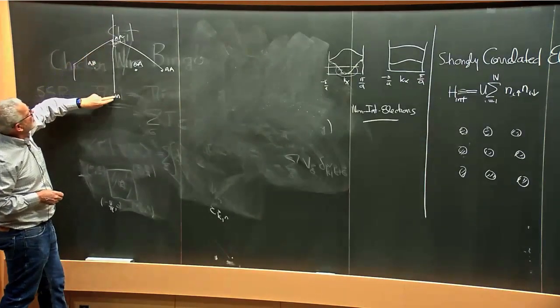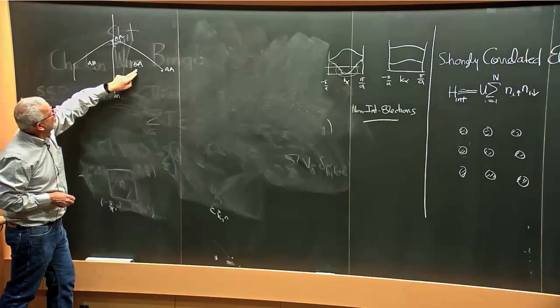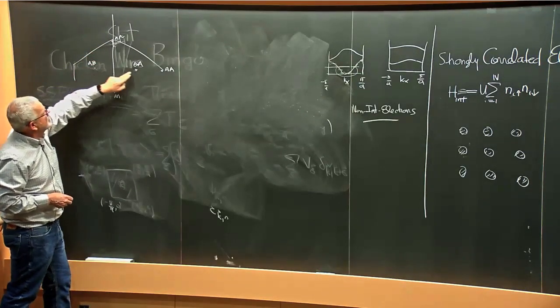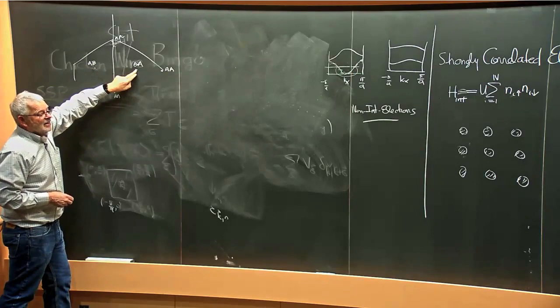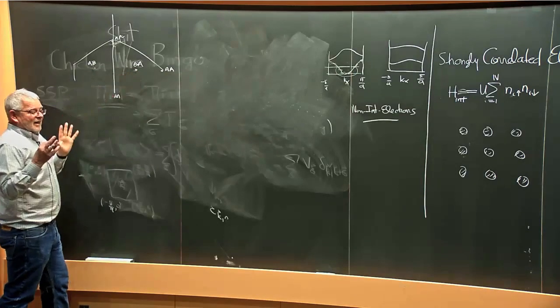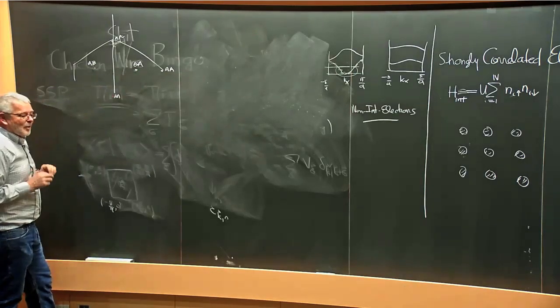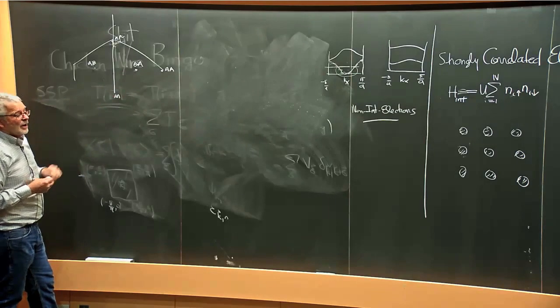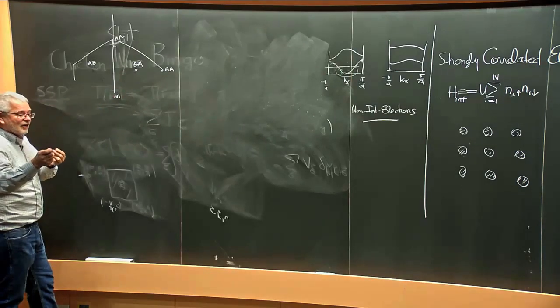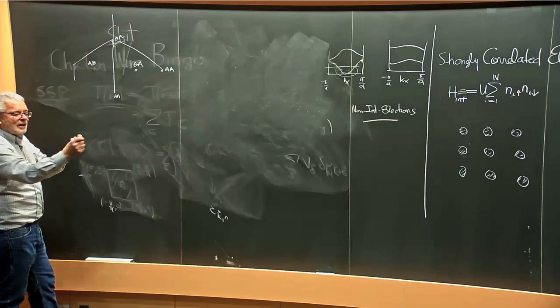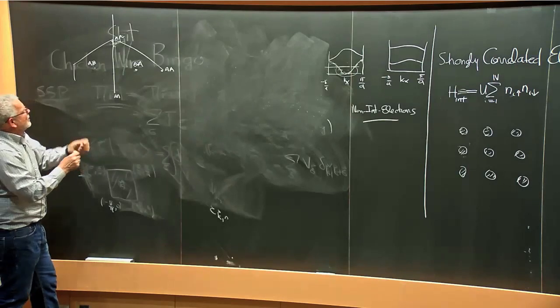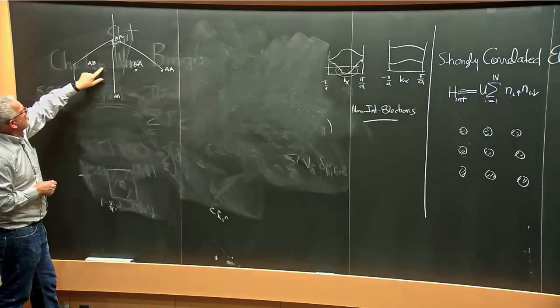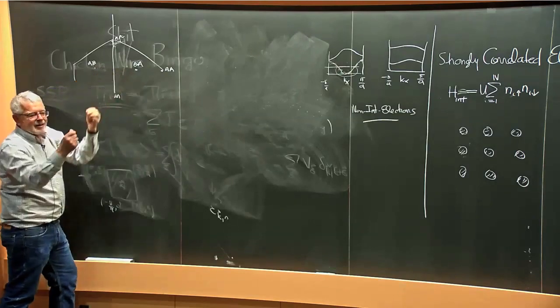Everywhere along this line that's the perpendicular bisector of AB to BA, there are two points in momentum space at which you have linear band crossings, and those two linear band crossings, as you go away from this point towards here or here, approach each other and go to zero. So the band structure changes in a complicated way as you go through momentum space.